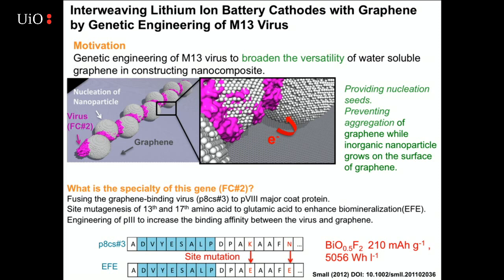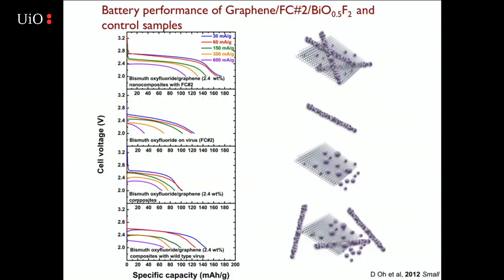And so this material was bismuth oxyfluoride-based material. And we found only when you had the virus in contact with the graphene plus growing the material, you had the best kinds of data. So now you're looking at specific capacity. And this is actually looking at the virus with growing the bismuth oxyfluoride by itself. This is actually looking at just precipitated bismuth oxyfluoride with graphene. This is growing the two together, and then this is actually growing them separately and then putting them together. And it was when they were in the closest contact that we had the best kind of data.